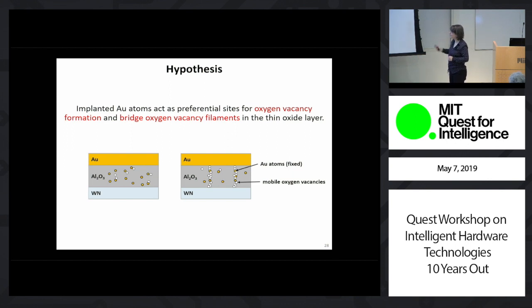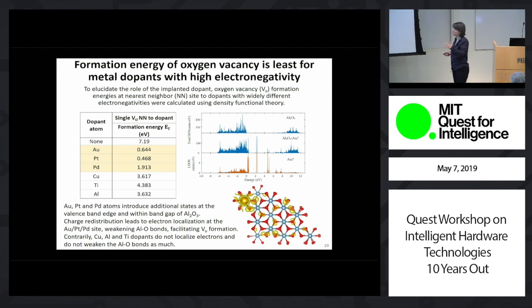Okay? So if that's the hypothesis, we can actually test this hypothesis systematically by changing the metal that we implant into the alumina layer. And it's easier to do this first computationally, or to test this first computationally. And we have varied the metal that we implant from metals that like electrons more, so more electronegative metals like gold, platinum, palladium, and contrast them to other transition metals which are not as electronegative, like copper, titanium, and aluminum.